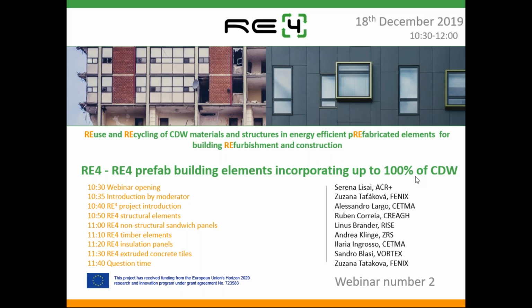And also, of course, in dimension, you can transport and store these a little bit tighter. Another benefit with carbon textile reinforcement is that it doesn't corrode like steel reinforcement can do. So every solution has its pros and cons, but these are some of the benefits of it. So I would say making it more corrosion resistant and reducing the weight would be the major. And it's interesting to see that we managed to do this high performance concrete using this textile reinforcement also in these panels.